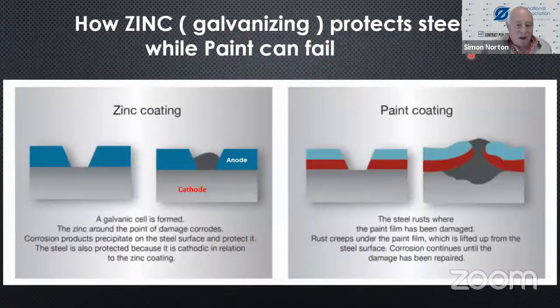If you look at the coating on the left-hand side, again, the chemistry of zinc comes into play. The zinc coating is the anode, the steel is the cathode. The zinc forms corrosion products. If you've got a scratch or damage in your zinc coating, it blocks it up. The zinc is the anode and then oxidizes and protects the underlying steel.